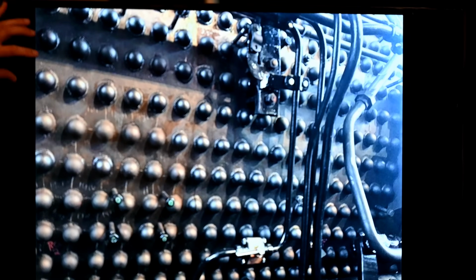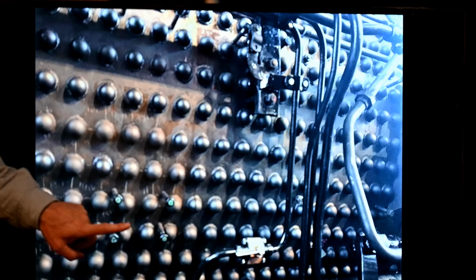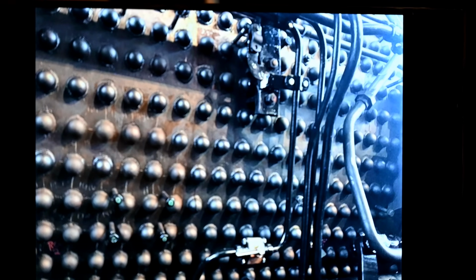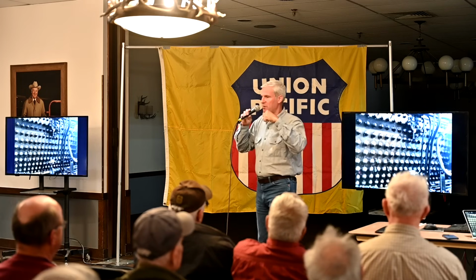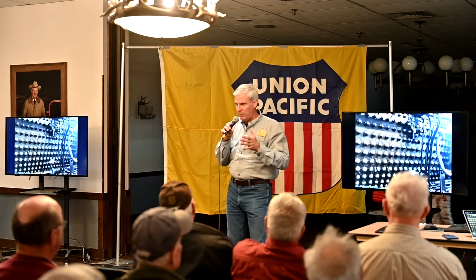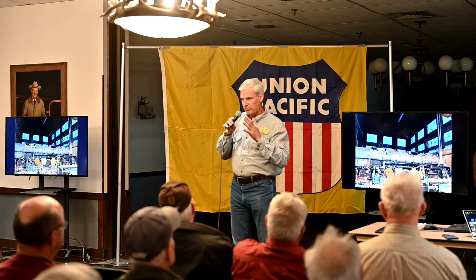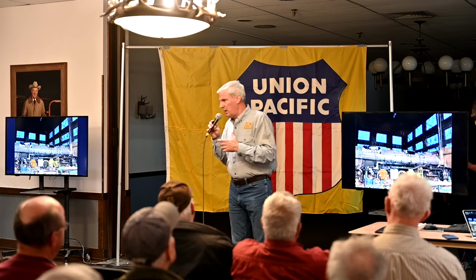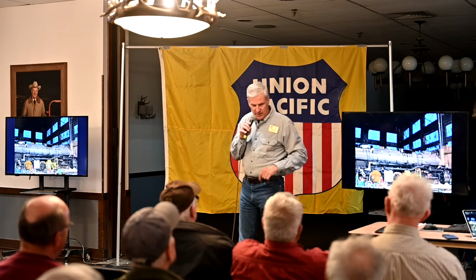These are the actual caps. On the boiler, this plate is 1.5 inches thick, and thicker in some cases. All of the stay bolts are inside each one of these little caps that make it steam tight. They have a little ball head, so it's flexible. When the locomotive steams up in the morning, it's in a cooler state. As you heat it up, it begins to expand, and those flexible bolts allow for a little bit of movement. If you didn't have that, the locomotive's so big, it would break so many stay bolts, it just wouldn't be economical.